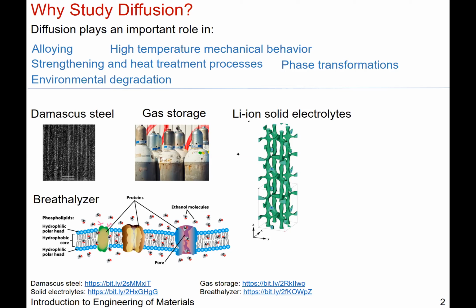And what's coming online is lithium-ion solid electrolytes. As you know, the current technologies that we have right now, used mostly for rechargeable mobile devices, mostly use lithium-ion technology that have liquid electrolytes in them. And so electrolytes are just salt in some sort of solvent, right? So the salt is typically something like lithium hexafluorophosphate, so that's LiPF6. It's usually in a carbonate-based electrolyte. It's quite corrosive. Actually, over time, the stainless steel can become brittle and corrode. That's not for a long time though, and that's actually not your big problem. Your big problem is that you're using liquid electrolytes as it is.